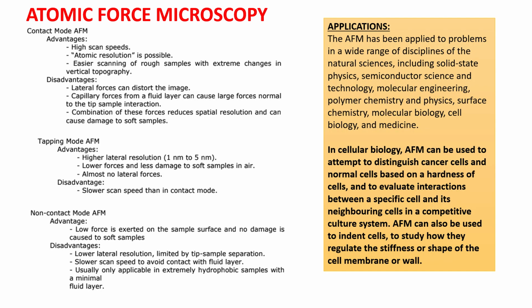So this is a briefing of all the different modes and their advantages. The contact mode has the advantage of high scan speed, but the disadvantage is that it can distort the image or the sample, and it cannot be used for soft samples. For tapping mode, the resolution is higher, but the speed is much slower compared to the contact mode. For non-contact mode, no damage is done to the sample, and therefore it can be used for soft samples like cells, but